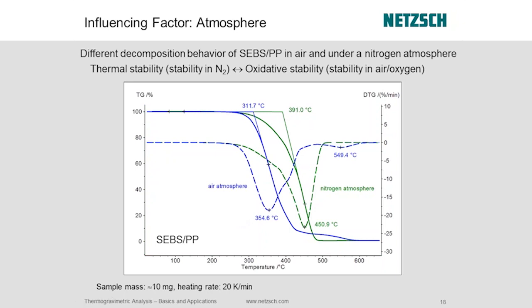Pretty neat. This is a comparison then in air, and you can see it behaves quite a bit differently. First of all, this blue is similar to that solid curve with the green. This is your mass loss curve, and you can more clearly make out that there's two steps going on here. We saw something in the derivative for the nitrogen curve. Maybe you can even see it here. There's kind of a shoulder here. So it looks like a couple of steps going on, but it's hard to make out under nitrogen.